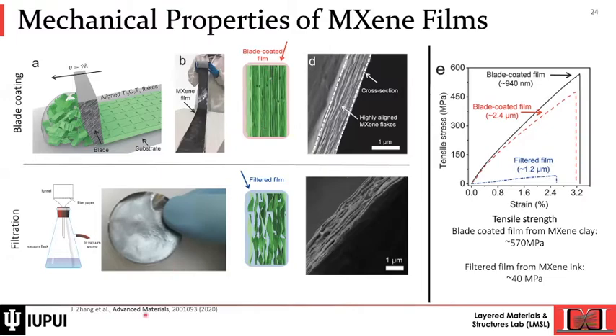Here's a nice study published in 2020 that showed how you prepare your MXene film, whether it is blade coating, which leads to better alignment of the flakes, versus vacuum filtration. If you use high concentration in vacuum filter, then the film will be less aligned. The MXene flakes will be less aligned. That will significantly change the resulting MXene, for example, tensile strengths. So both these films were basically measured, pulled, and the tensile stress was measured. You can see the blade coated film of only 1 micrometer had the tensile strength of about 600 megapascal, but the vacuum filtered film that has these misaligned or disordered flakes had only 40.